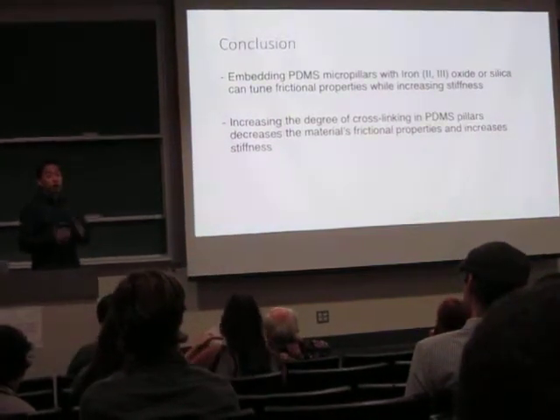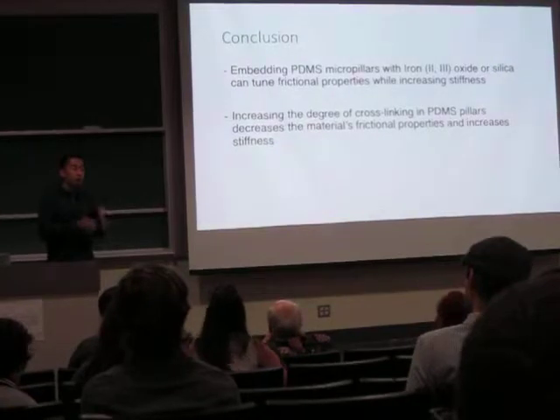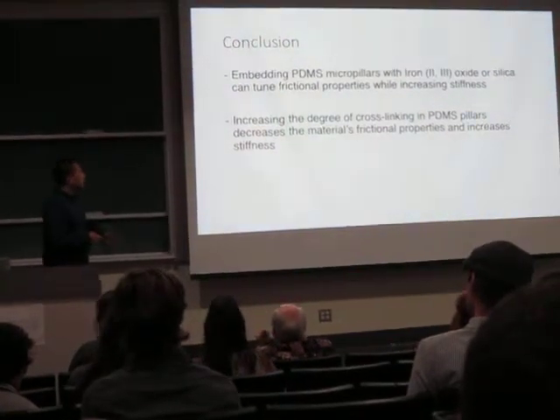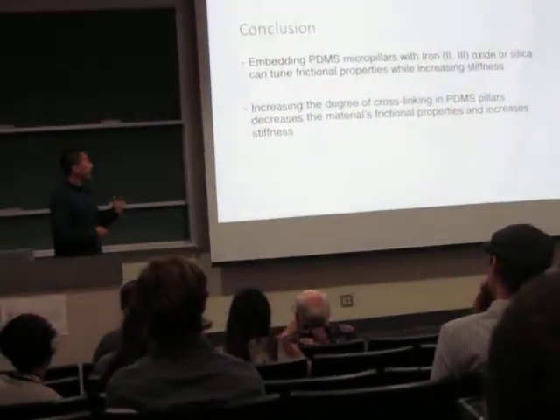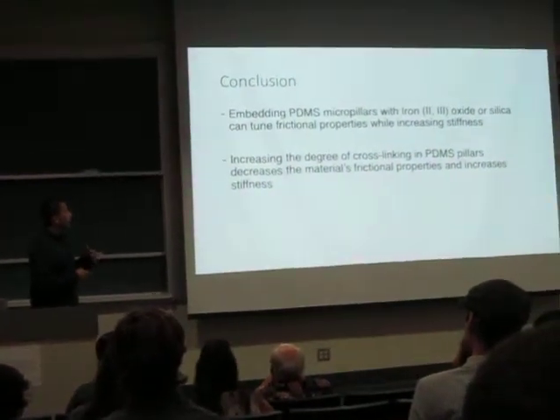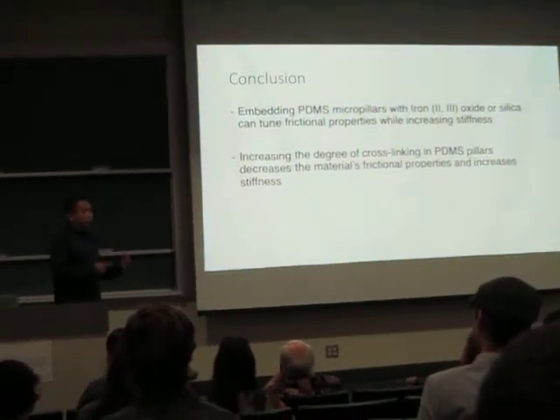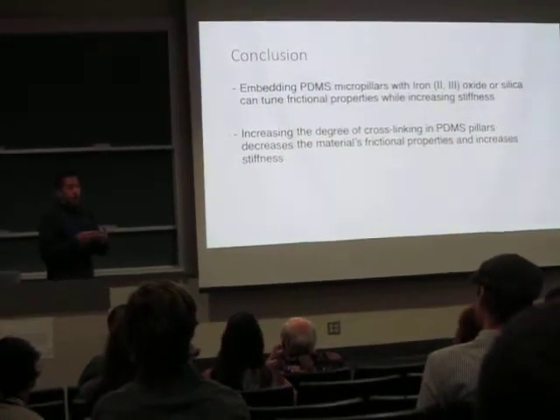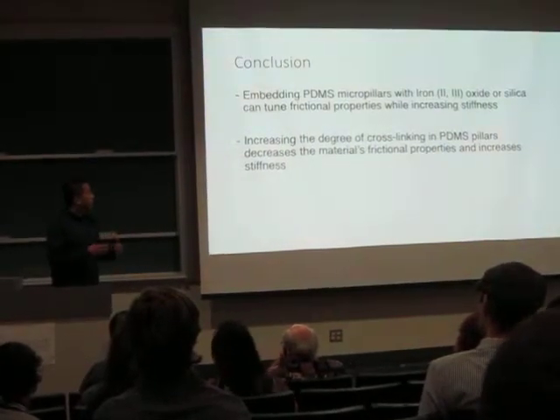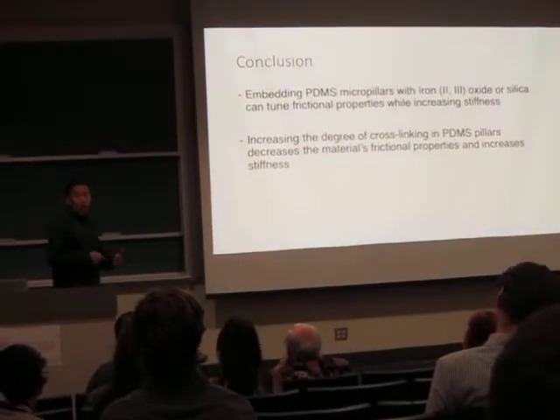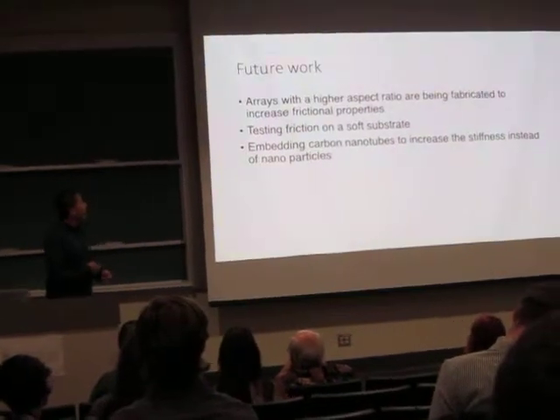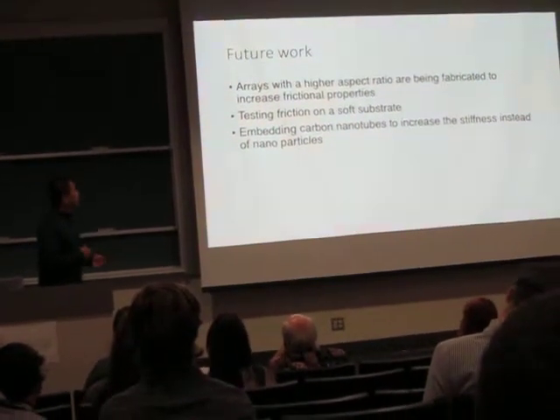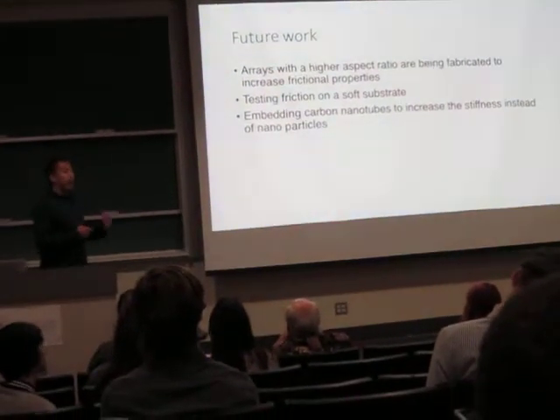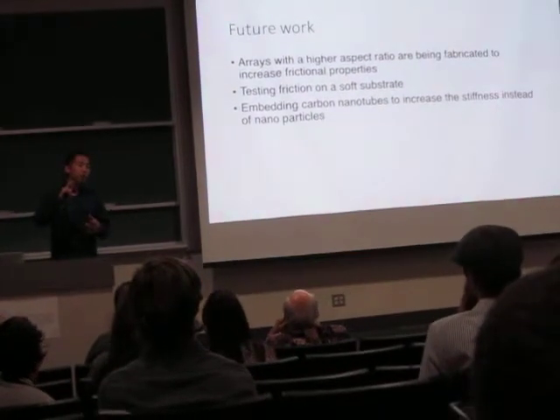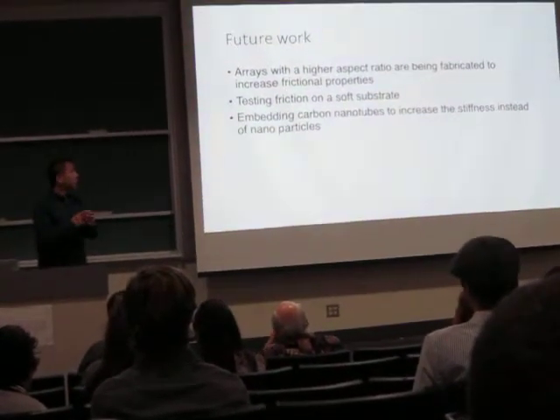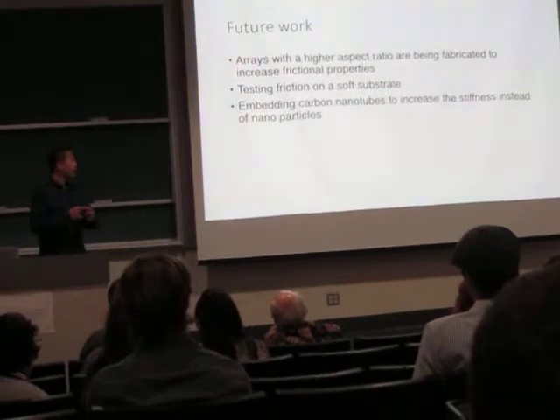And we don't know for sure if it's the particle size or the particle itself. So our assumption so far is that it's the size. And also we can add more curing agent to create a cross-linking structure and make the PDMS stronger. And our future work is we're going to change the aspect ratio, which is the length of the pillar over the diameter of the pillar.